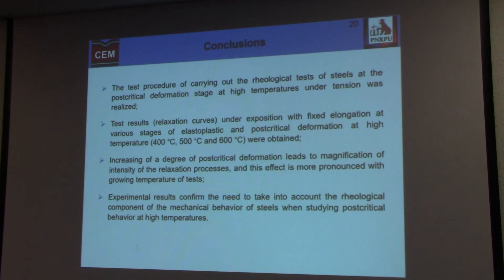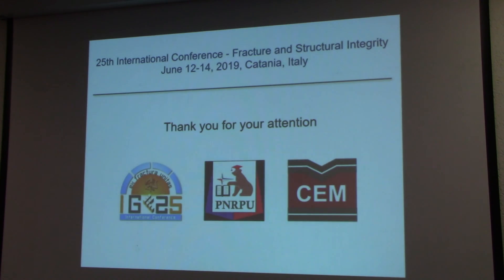In conclusion, I can say that the test procedure of carrying out the rheological tests at the post-critical deformation stage at high temperature was realized. Test results under exposition at higher stages of post-critical deformation were obtained. And it is shown that the increasing of the degree of post-critical deformation leads to magnification of intensity of the relaxation processes. And this effect is more pronounced with the growing temperature of tests.